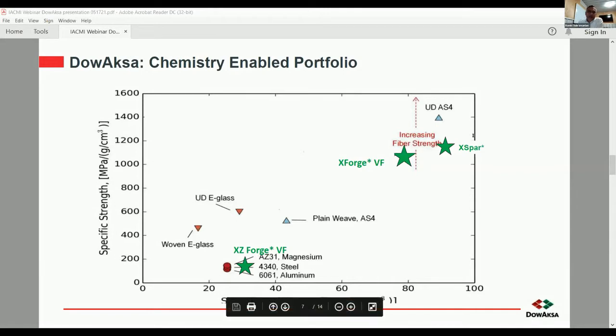And XSpar is our laminate. So this is about as close to the pure carbon fiber performance as you're going to get. This is about 70% all carbon fiber by volume. So the business case for the laminate is well proven. We have several large OEMs as our key customers, and the carbon fiber is actually in the spar cap. So that is a spinal column, if you will, of the wind blade.